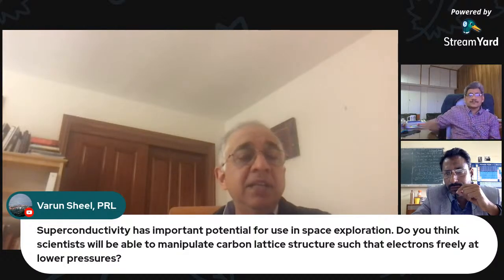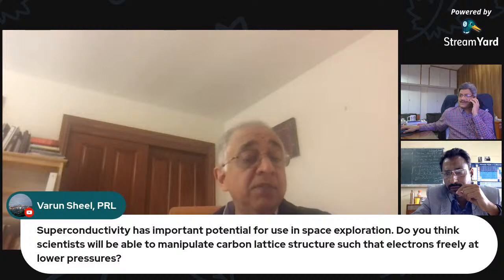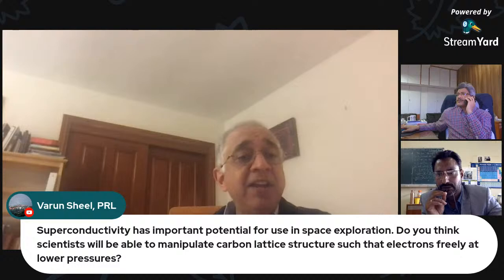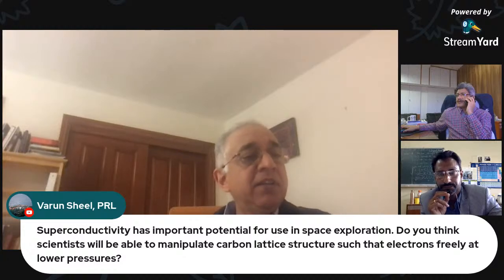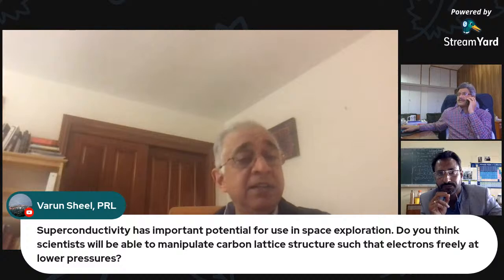So these high pressure, room temperature superconductors, actually carbon is a minor player there, but hydrogen is a very important player there. And the idea for making high transition temperature superconductors using hydrogen came from the work of Neil Ashcroft, a very famous condensed matter physicist whose book Ashcroft and Mermin many are familiar with. But he was actually thinking about an astrophysical problem. He was thinking that if hydrogen under pressure becomes a metal, normally if you sufficiently cool hydrogen, it's a molecular solid, H2. But under pressure, it metallizes rather than being a molecular solid insulator. And that metal actually becomes a superconductor. And Ashcroft and others thought that this might be relevant to what's happening on Jupiter.